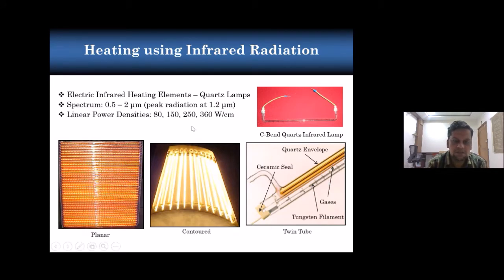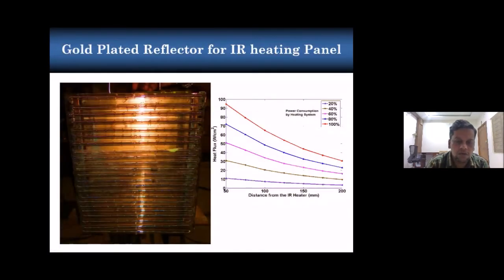Now these are the various linear power densities we are using. Over this short wavelength range, our lamps can emit maximum peak power at 1.2 micrometers. Now this is one gold coated reflector assembled with IR lamps. You can see here, as you go away from the heater, our flux will come down drastically. At 50 mm distance from the heater, at rated power, I can get a maximum of 95 watt per centimeter square flux.